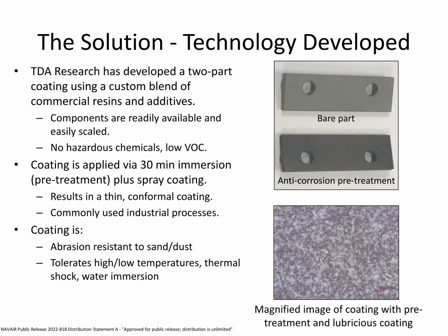As I mentioned, the coating is a two-part system consisting of a 1 to 2 micron thick lower layer that is intended to protect against corrosion, and a 3+ micron thick top coat that's an organic polymer with anti-friction particles incorporated into the polymer composite. The process has changed a little bit now. The pre-treatment is a 5-minute brush plating instead of an immersion. We get better coating that way. It's a thin conformal coating.